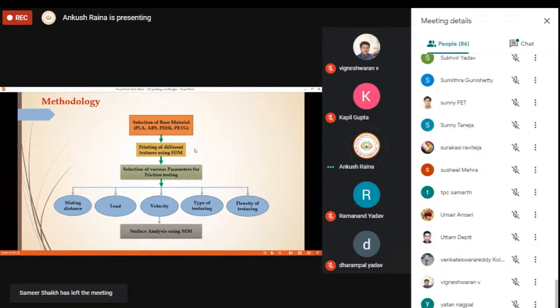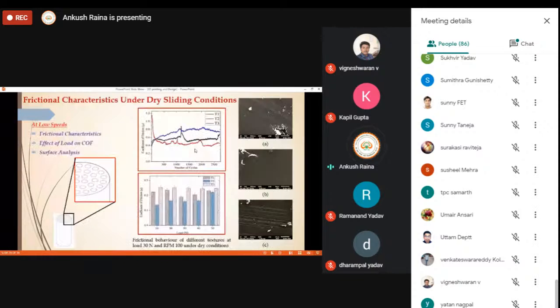So the frictional characteristics under dry sliding conditions, first at the low speeds, you can see we have the pins like this, and this is a zoomed view of the pin which is shown over here, and you can see the textures over here. We generated these textures on those pin surfaces, and we tried to study the frictional characteristics, the effect of load on COF, and we tried to do the surface analysis.